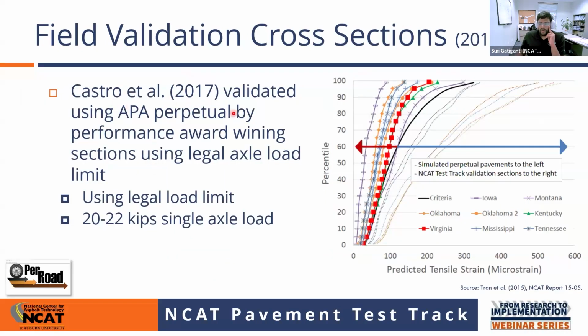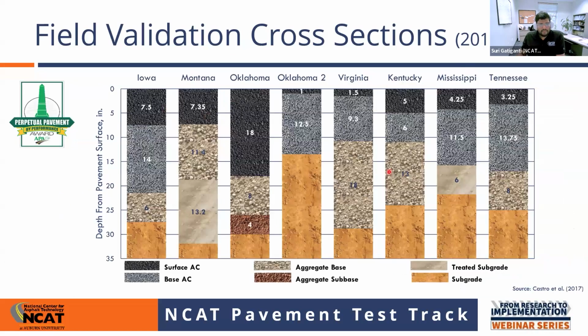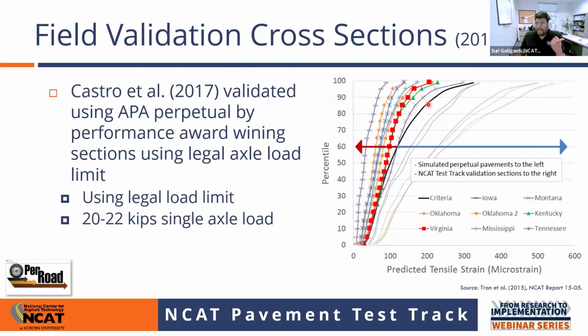Castro, Alfredo. So what they did is basically, this dark solid line you're seeing is the criteria that was proposed in 2015 by NCAT, and all the test sections which won the APA Perpetual Award, which saw good life with no deterioration or structural damage, were actually falling on the left side of that line, which is where they're supposed to be if they are performing perpetually. So what they did in 2017 is validate the criteria given in 2015 using actual sections out in the field.